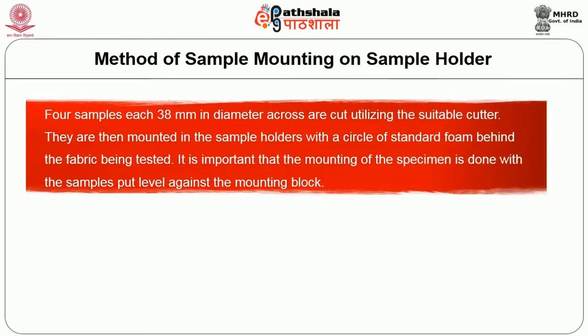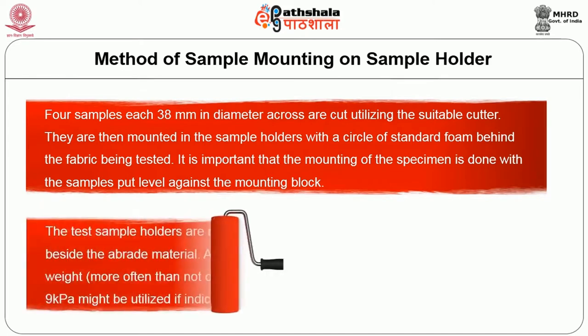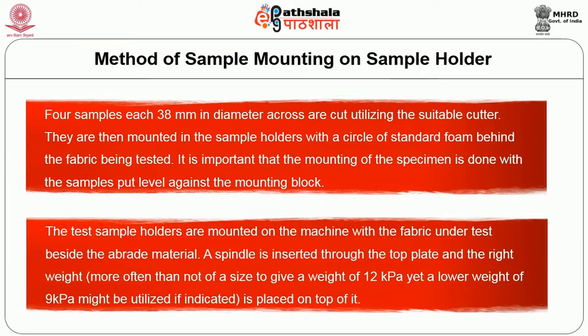The procedure for mounting the sample in the Martindale abrasion tester: four samples, each 38 mm in diameter, are cut utilizing the suitable cutter. They are then mounted in the sample holders with a circle of standard foam behind the fabric being tested. It is important that the mounting of the specimen is done with the samples put level against the mounting block. The test sample holders are mounted on the machine with the fabric under test beside the abradant material. A spindle is inserted through the top plate and the right weight. More often, it has a specification of weight of 12 kPa, yet 9 kPa can also be used if needed for specific types of fabric.